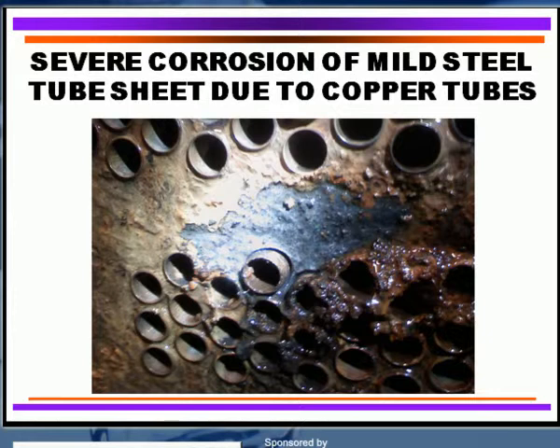Here's an example of really serious pitting attack between the actual tube and the tube sheet. In some cases you have the tube extending further out than it would normally be, but you can have penetration, corrosion product buildup, plugging in the tubes, and possible leaks between the tube and the tube sheet, and that would mean that the refrigerant would be lost.